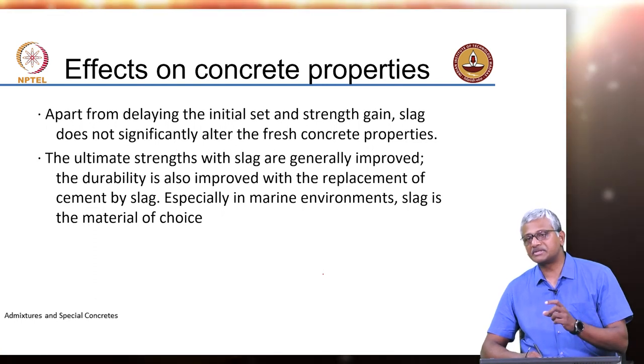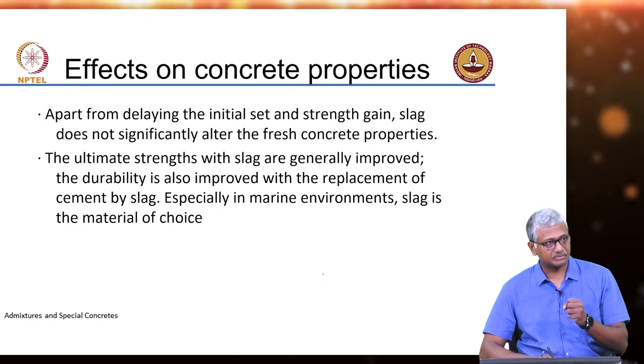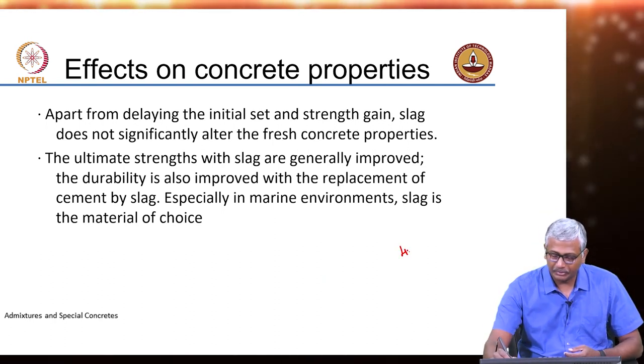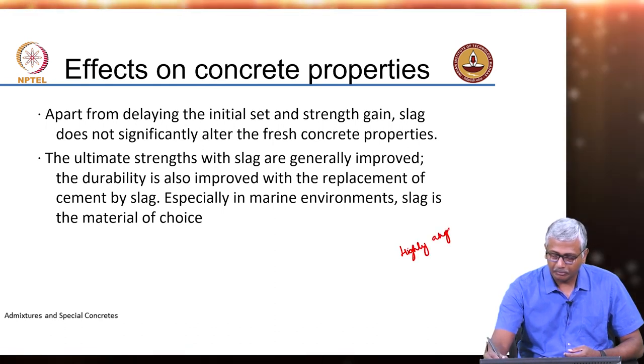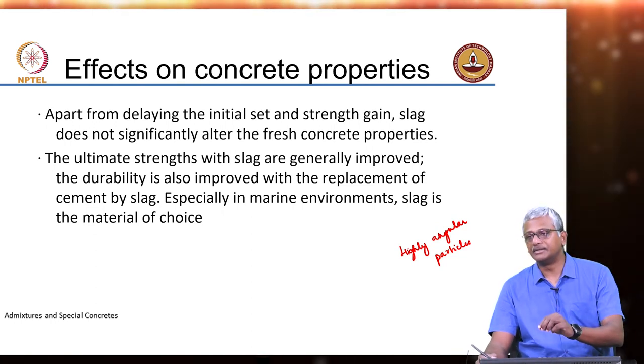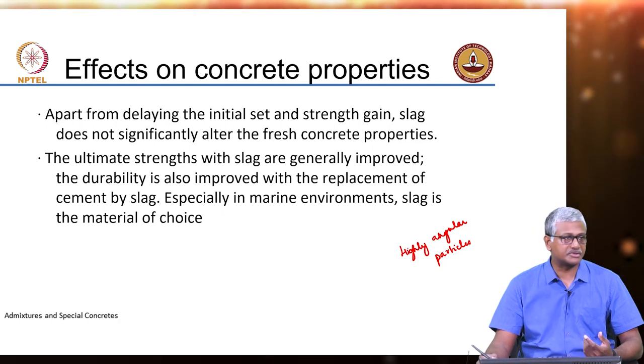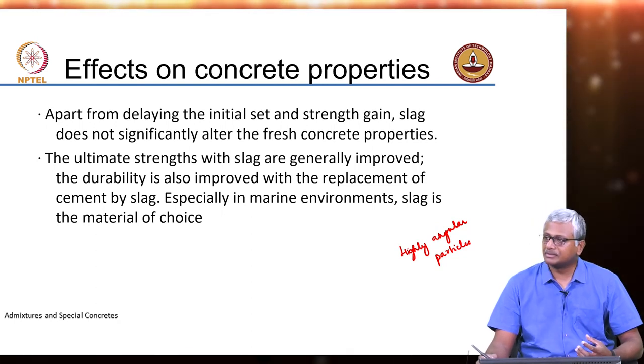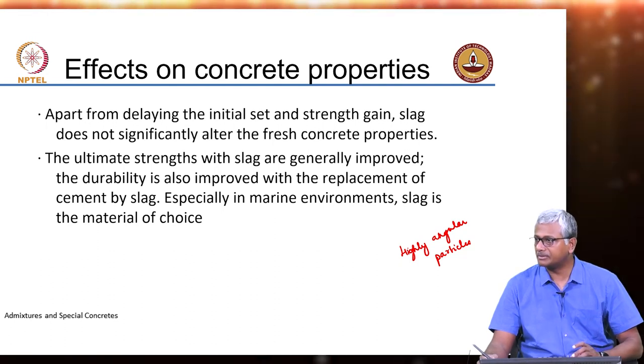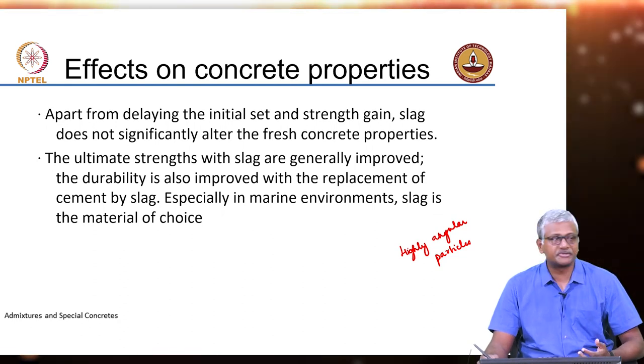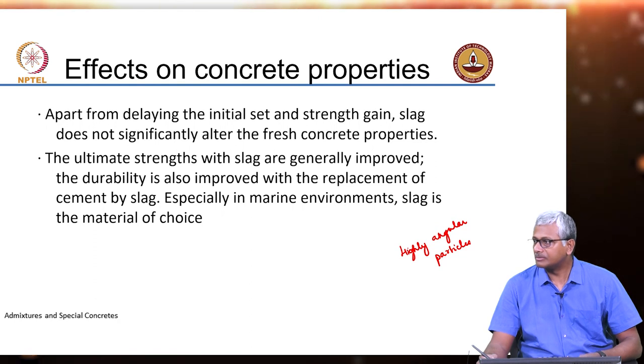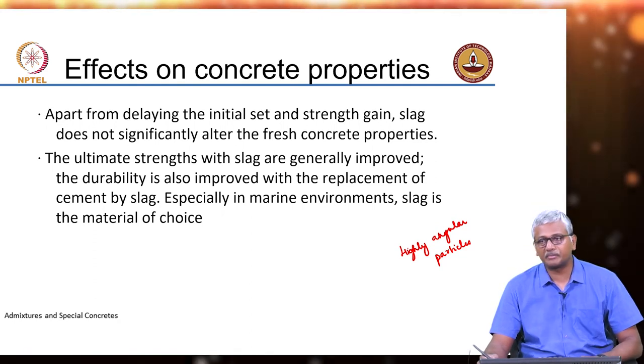One thing that may happen — please remember slag is a ground version of the granulated slag that comes out after quenching the molten slag. When you grind it, these particles become highly angular. Of course cement grains are also angular, but please remember that slag is much harder than cement. We talked about it from the perspective of inter-grinding versus inter-blending. So because of this hardness, slag particles can actually increase the harshness of your system. When you are trying to pump slag concrete through a pipe, the frictional resistance will be more, and pipes seem to get worn out much faster as compared to plain cement concrete. So you are basically pumping a harder material, so wear and tear of the pipe is going to be much more.